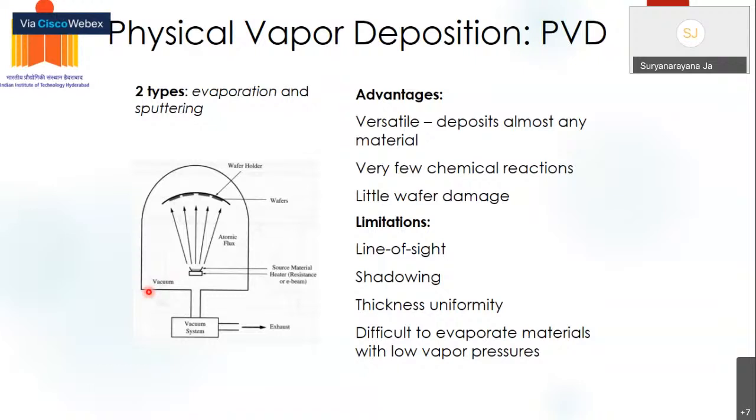Okay, in the physical vapor deposition system, the main important things are a chamber and a vacuum system. The vacuum system is the one which will suck the air molecules from the chamber. Once you feel like you have acquired a reasonable amount of vacuum in the chamber, then you will try to deposit. The vacuum levels you would expect are of the order of 10^-6 torr. And once you create the vacuum within the chamber, you would have a boat on which you will put your desired material, and then heat this boat